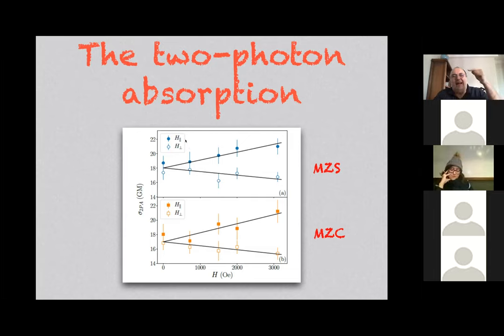Just to explain what we are doing: we are putting the electric field of the laser beam parallel to the magnetic field or perpendicular to the magnetic field. And with this, we measure the sigma 2PA. So parallel and perpendicular means parallel or perpendicular electric field and external magnetic field. So we see the anisotropy that we see here, which depends on the intensity of the field. So here's the cross section, and here is the intensity of the field that we are able to put in the sample. It increases with increasing the magnetic field.